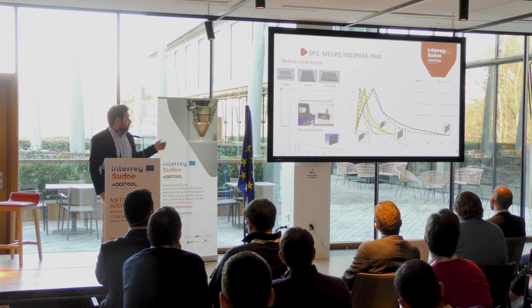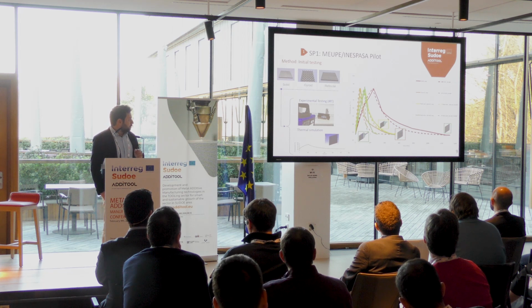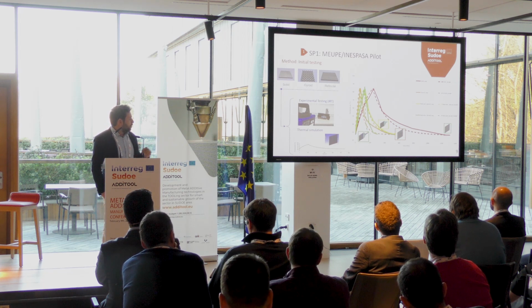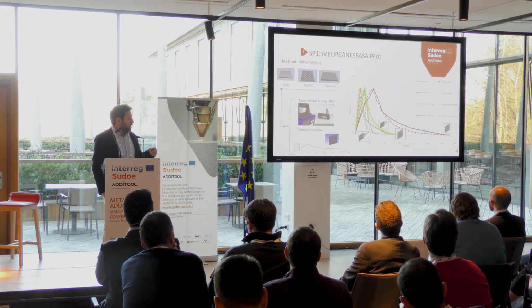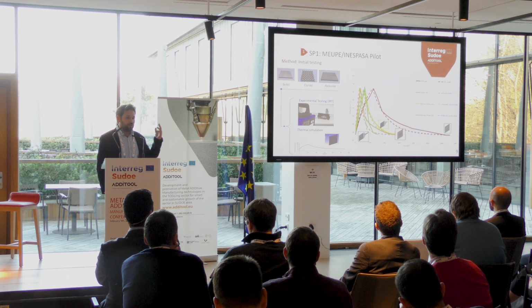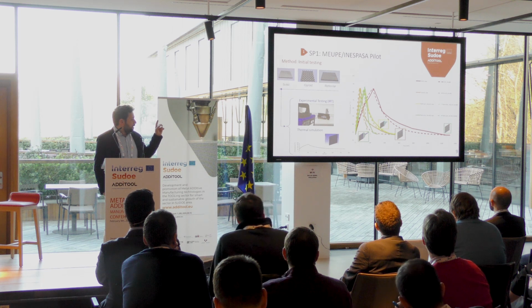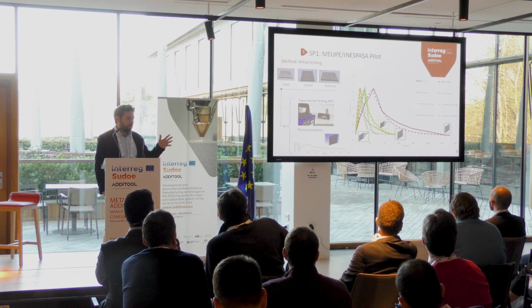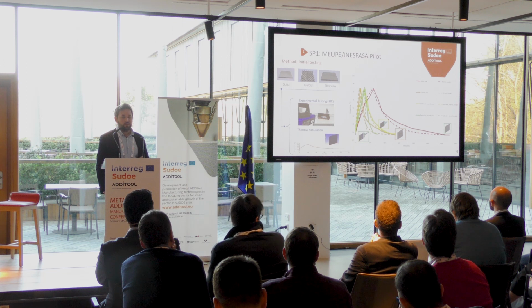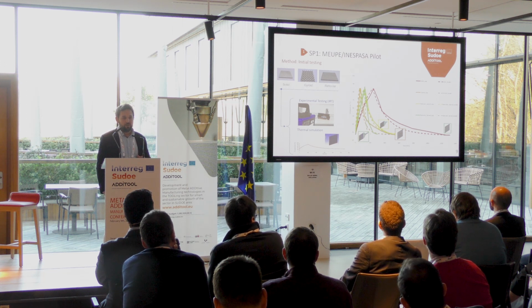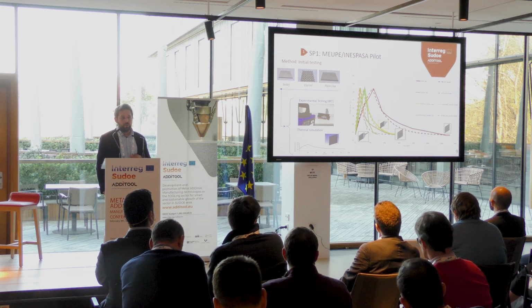So as you can see, comparing the orange with the yellow, the gyroid structure reaches 85 degrees faster, but in the cool down process, they reach 28 degrees at the same time as the reticular, which means it has the capacity to absorb that heat, but then difficulty releasing that heat.